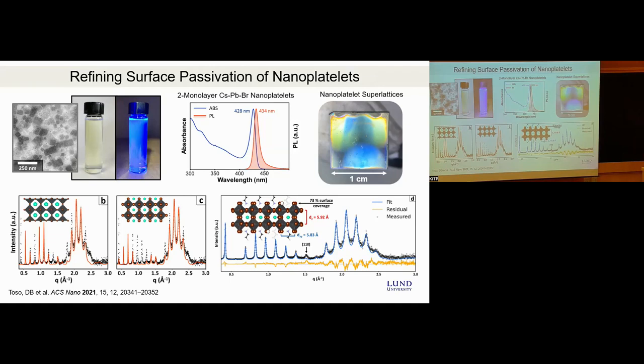What's the shape of these nanoplatelets? These nanoplatelets are quite irregular. They are large and very uniform in thickness, but the dimensions can be 100 by 100 nanometers. So they're essentially colloidal sheets, which then pack very nicely face to face. The thickness is one, two monolayers, so two octahedra.